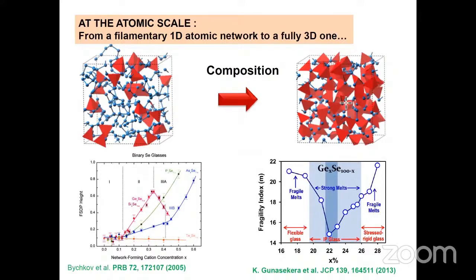And what is interesting is that many different physical, chemical, mechanical properties, or even optoelectronic properties change with this composition. For example, I showed here two typical examples. It, of course, impacts the structure, and we have just seen in the previous talk how the structure is affected by composition. Here for a family of selenides, the typical height amplitude of the diffraction pattern, the first sharp diffraction peak, how it changes with network forming concentration, germanium, silicon, or phosphorus. Or another quantity in the binary Ge-Se, you can see that even dynamic quantities which characterize the onset of glassiness, glass relaxation, how you can eventually detect anomalies, that is a minimum or a maximum in physical chemical properties.